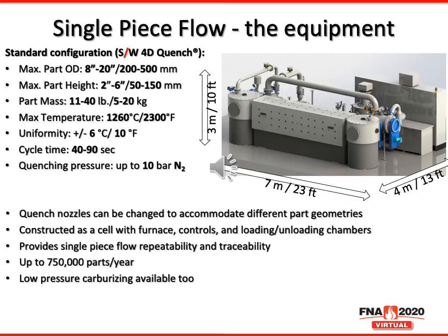What does it take to do this? Well, it's typically a piece of equipment that has the ability to move each piece through one piece at a time and then into the hardening chamber. Now, in this case, we'll take a look at the 4D quench technology developed by the Seco/Warwick. And here you'll find that this particular setup can handle up to a 20-inch diameter part that is up to 6 inches high with a mass of up to 40 pounds.